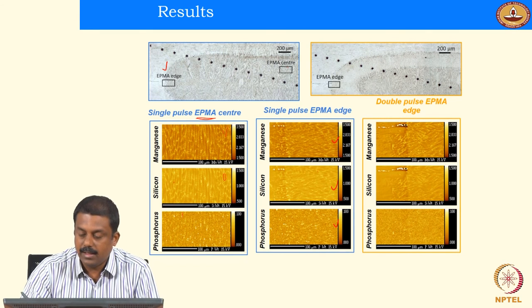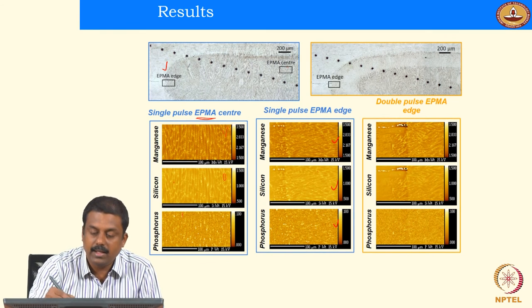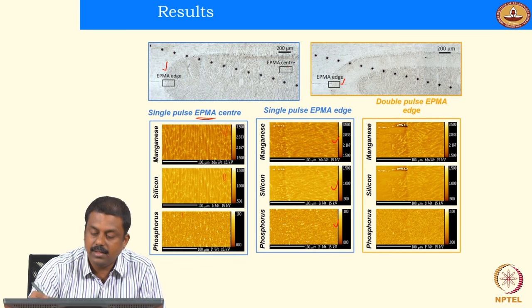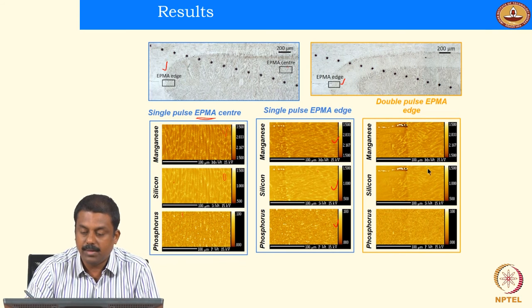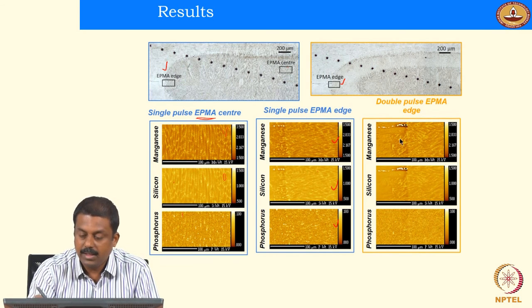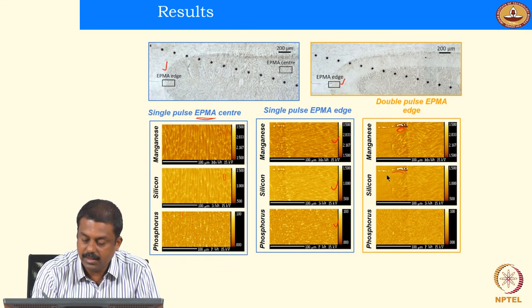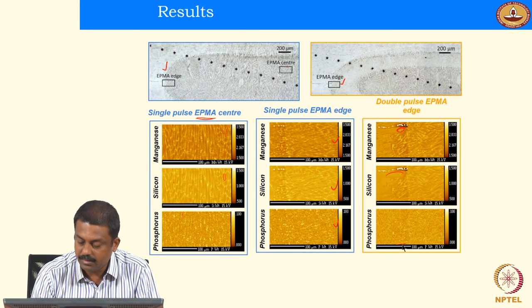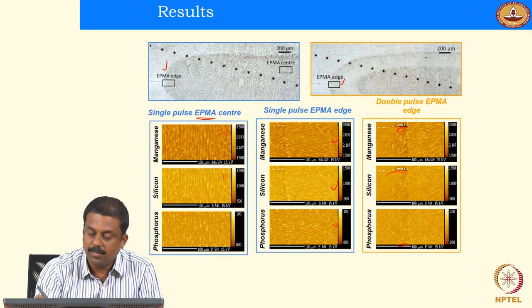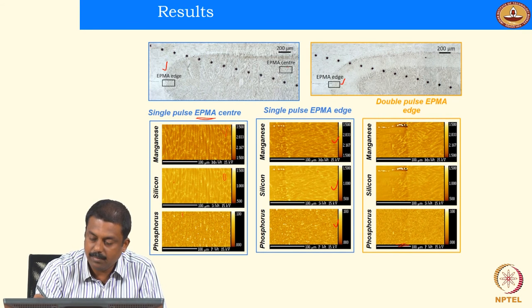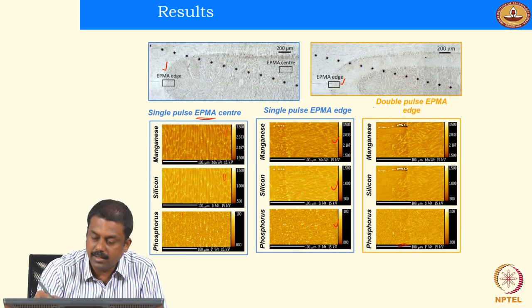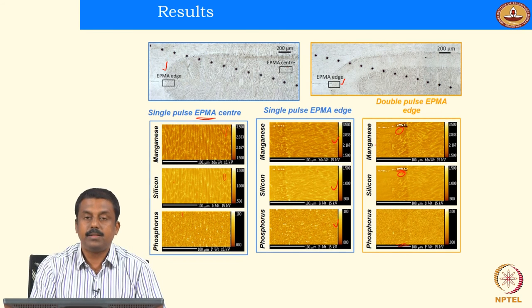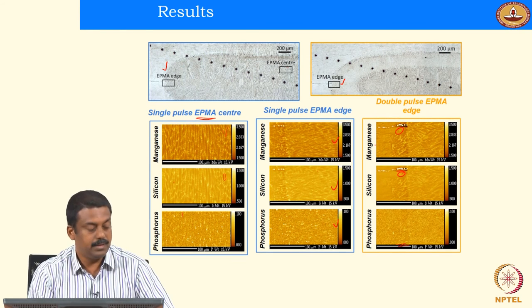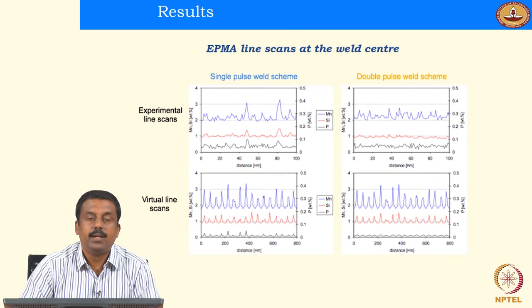Surprisingly, if you look at the elemental distribution at the edge regions after double pulsing, after the second pulse, you see already the regions are all homogenized. You see that there is no distribution. The phosphorus is distributed very homogeneously. Similarly, the amount of manganese at the weld center line sees a significant decrease. So that means that the double pulsing indeed homogenizes the segregation which actually formed, and